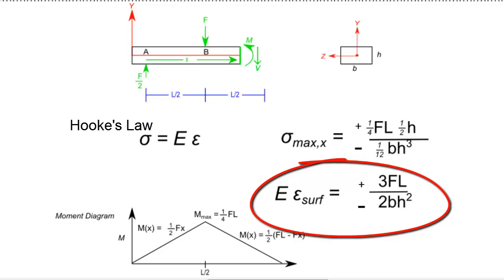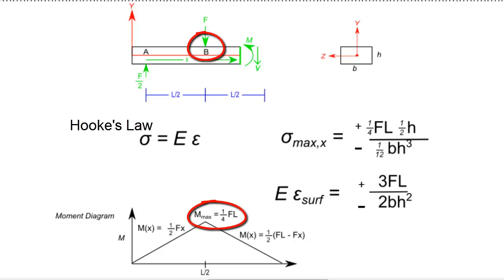While this is a relatively easy test to set up and analyze, there are some drawbacks to using 3-point bending. For one, the roller used to apply the load also causes a stress at the point of application, and this can cause premature failure. This risk is amplified by the fact that the point of application occurs exactly where the peak bending stress is also generated.